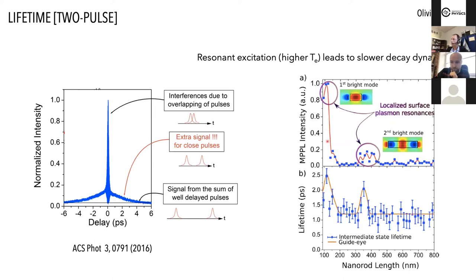And this is understood from the fact that at resonance, light is absorbed more efficiently, okay, which leads to a stronger electronic temperature, and a more elevated electronic temperature will also lead to a longer time for electron-phonon exchange. And this is exactly what we see in the measurements here. So everything seems to be consistent with this electron picture.